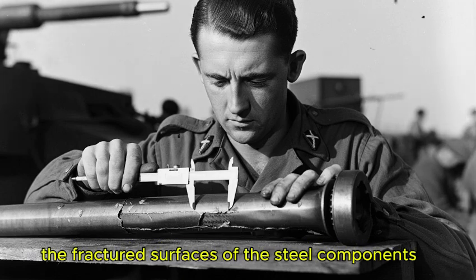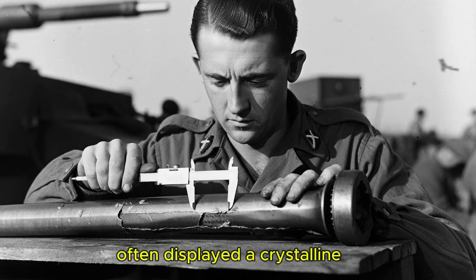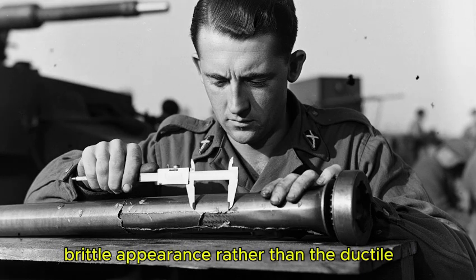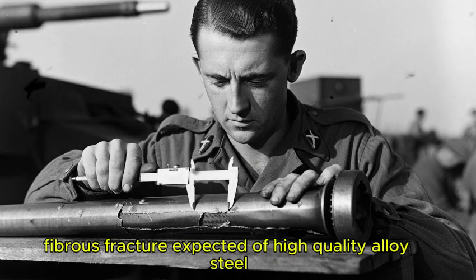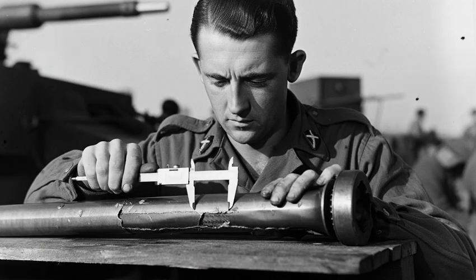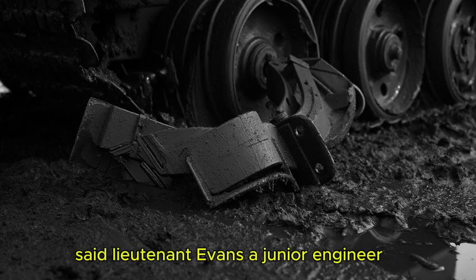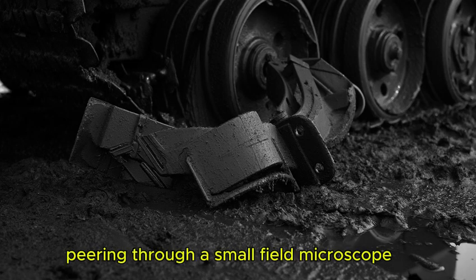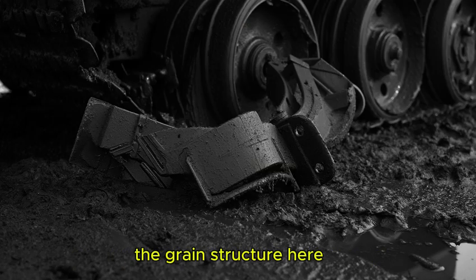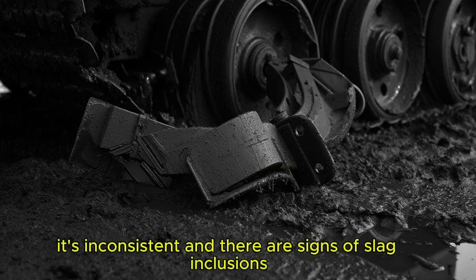The fractured surfaces of the steel components often displayed a crystalline, brittle appearance, rather than the ductile, fibrous fracture expected of high-quality alloy steel. "Look at this, Captain," said Lieutenant Evans, a junior engineer, peering through a small field microscope. "The grain structure here, it's inconsistent, and there are signs of slag inclusions, poor forging."